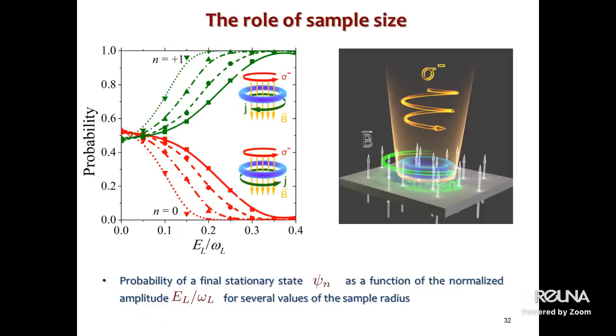Now I turn to analyze the role of sample size in the probability of the switching effect. Here, the figure displays how the radius of the ring affects the probabilities of realizing the stationary states, 0 mode and 1 mode, for the counterclockwise polarization. One clearly sees that rings with small radius achieve deterministic current carrying states at low amplitudes.